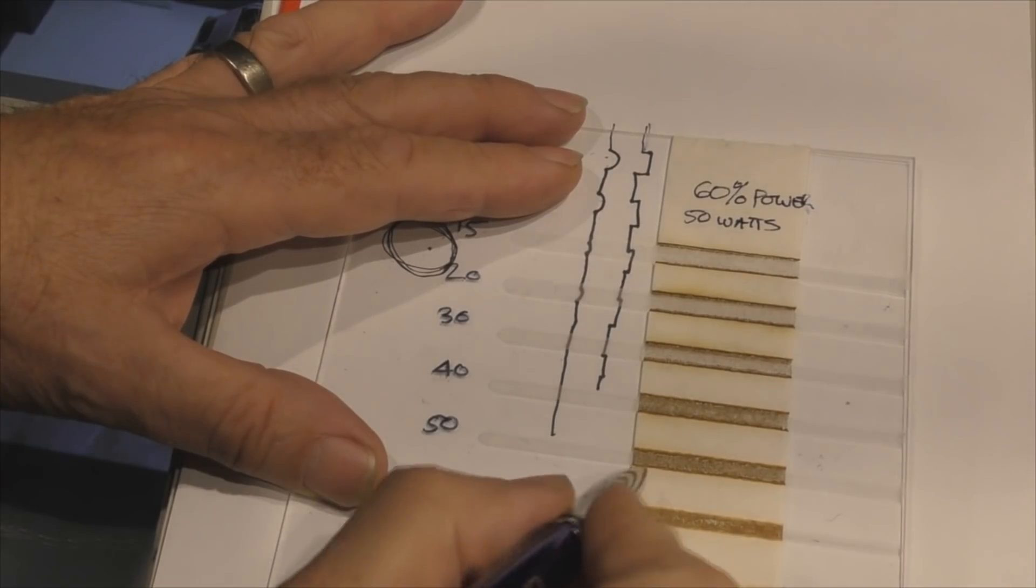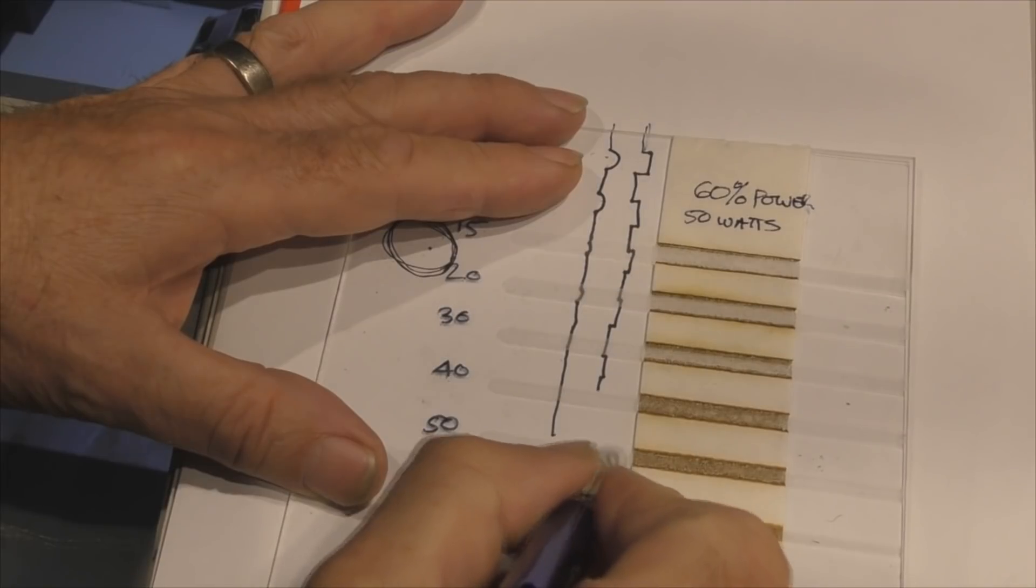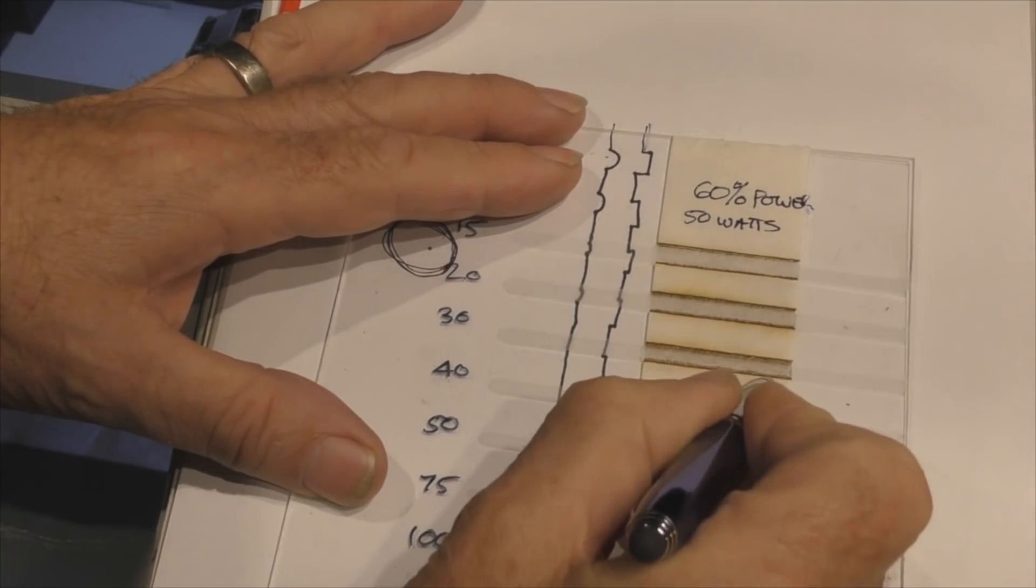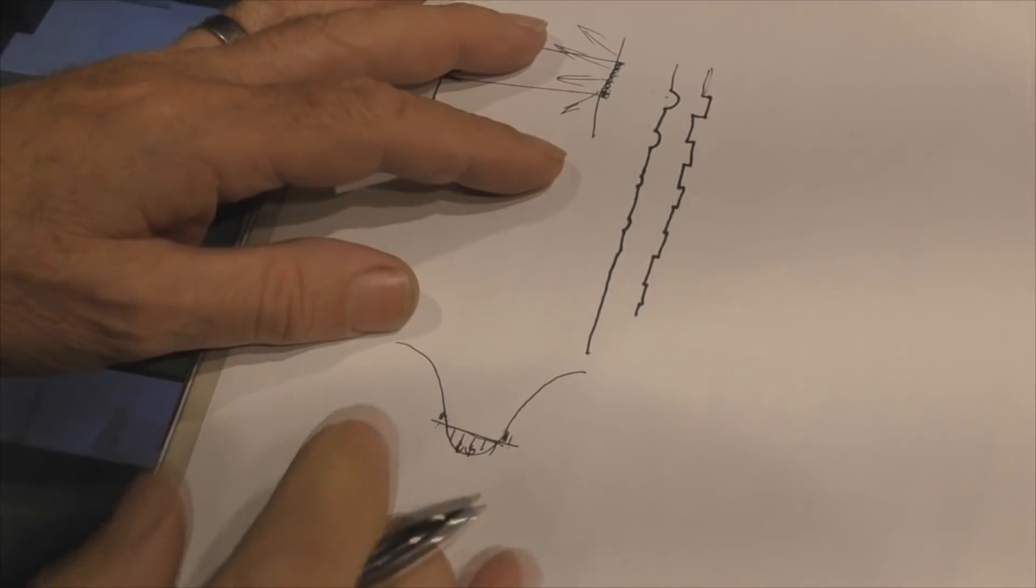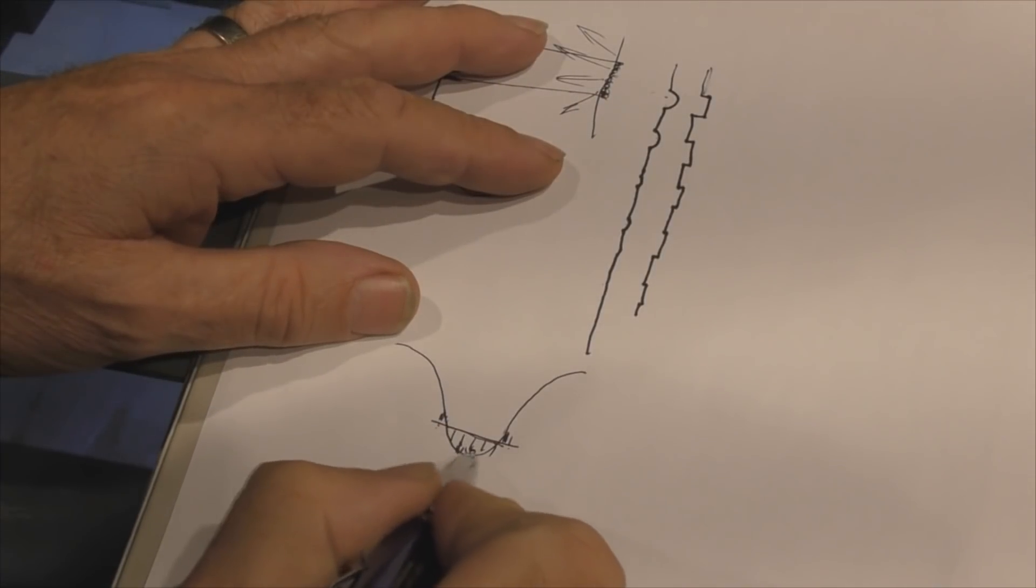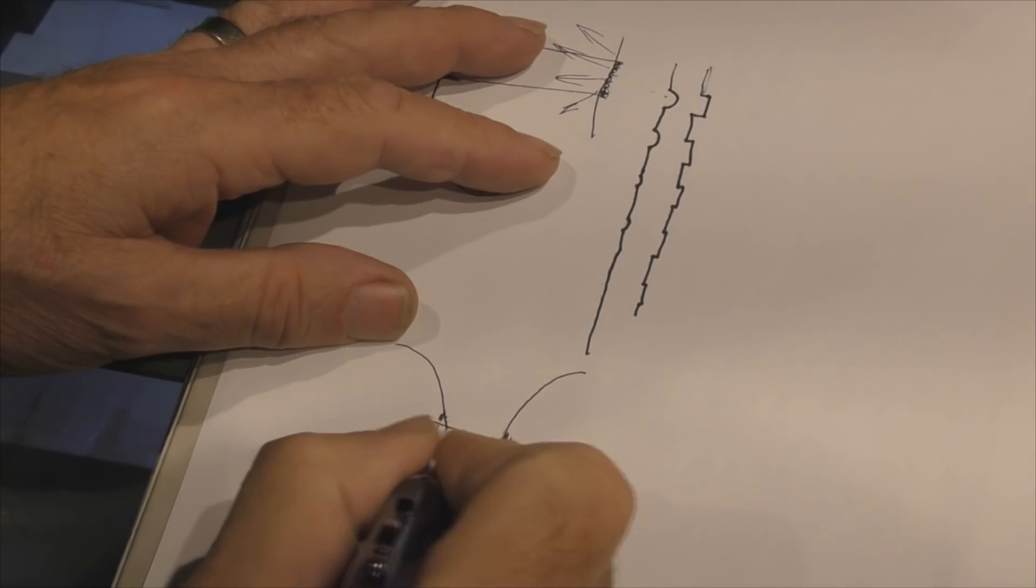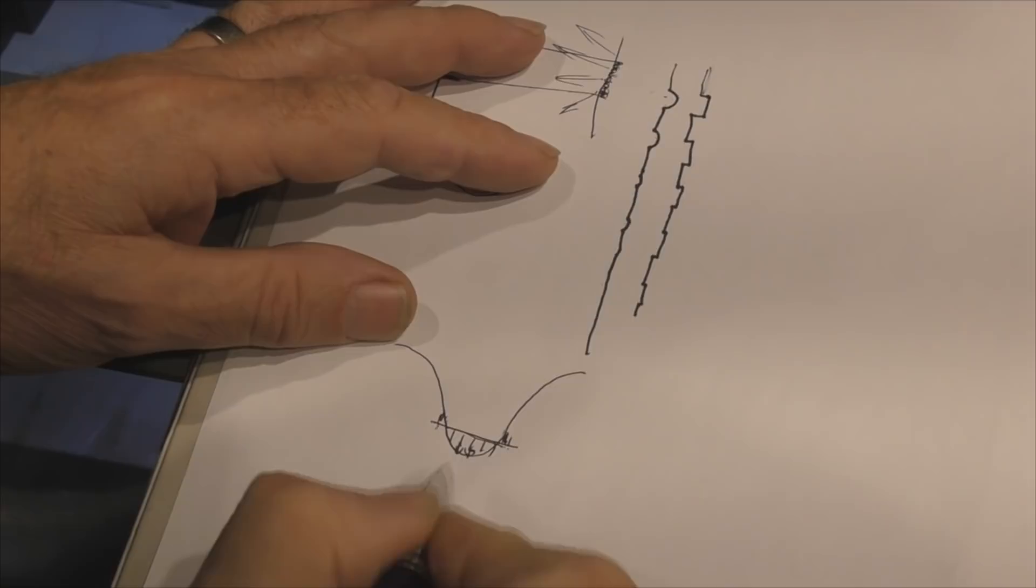And we can demonstrate that as we go up here, because if we look at each one of these burns, we shall see that not only have we got the burn width running through the masking tape, we've got a scorch mark, which is wider than the burn in every one of those instances. But it's only the energy density at the centre of this beam here which can generate high enough temperatures when it hits the surface to evaporate the material. But in these outer, lower energy density regions here, there isn't enough energy to evaporate the acrylic, but there is enough energy to scorch the masking tape.